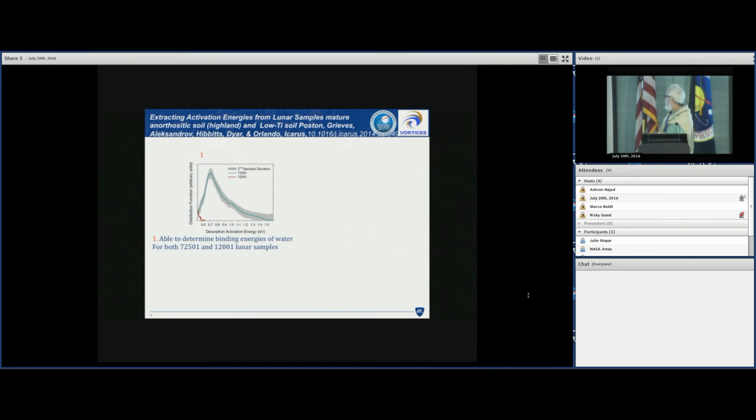Okay, so this is the binding energy distribution that you extract out of that, and it's sort of peaking here about 0.7 eV. Water on itself, or the water-water interactions, is just half an eV, a quarter of an eV per hydrogen bond. So it's slightly more strongly bound than water to itself, and then you have some states, but not many, that have higher binding energies. I'll get to this at the end. Actually, this width is a little bit narrower because we did some analysis where we have a diffusion component taken into account that narrows that width a little bit.